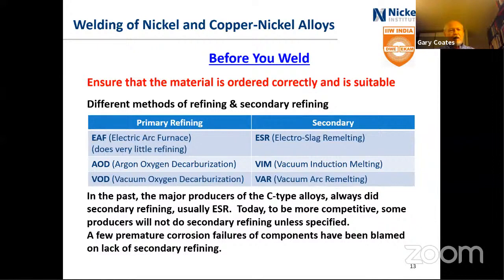Secondary methods of refining, once you've done the primary refining, are electroslag remelting, vacuum induction melting, and vacuum arc remelting. The latter two methods are more typically used on aerospace alloys rather than the corrosion-resistant alloys. The vast majority of them are secondarily refined in the electroslag ESR machine.